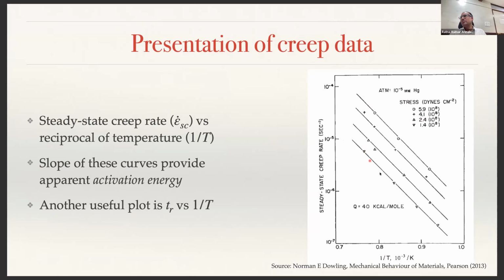This is at say 1.4 into 10 power 8 dyne per centimeter square. This is at 5.9 into 10 power 8 dyne per centimeter square. As you increase the stress, you can see steady state creep rate is increasing. And the slope of this line will give you something called activation energy.